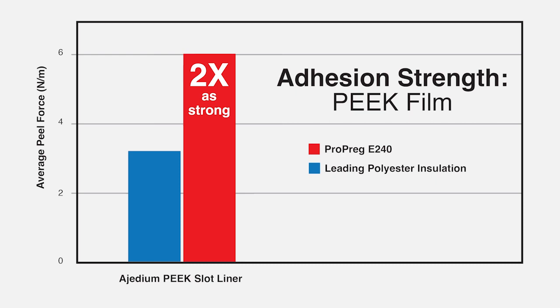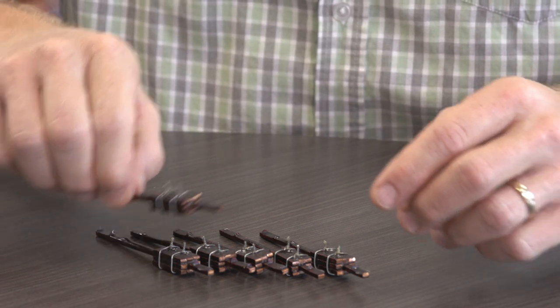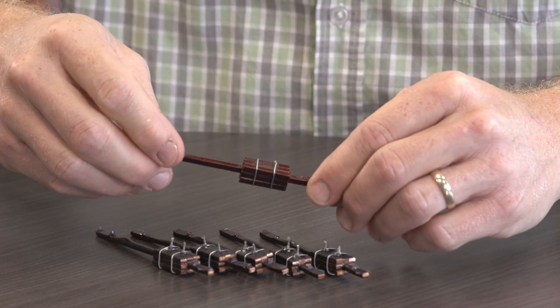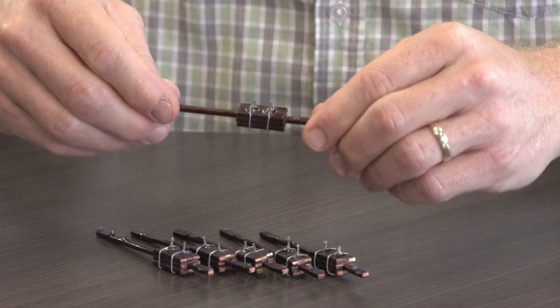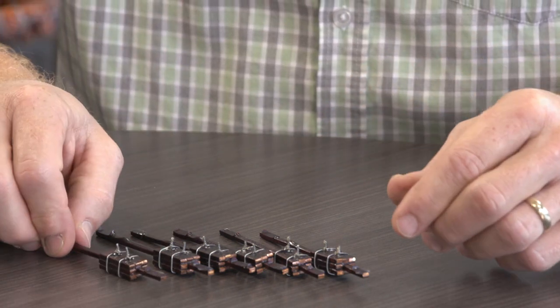Adhesion alone does not assure success as a secondary insulation. Adhesion must be maintained when exposed to elevated temperature conditions and applications using oil cooling. For secondary insulation materials, adhered wire bundles are tested using IEC 61033. These bundles are exposed to elevated temperature ATF and elevated temperature ATF vapor at 150 C.